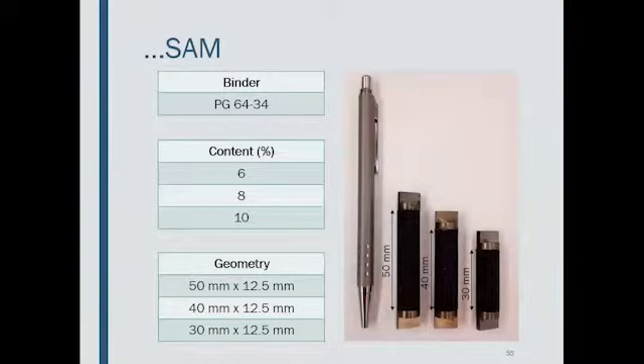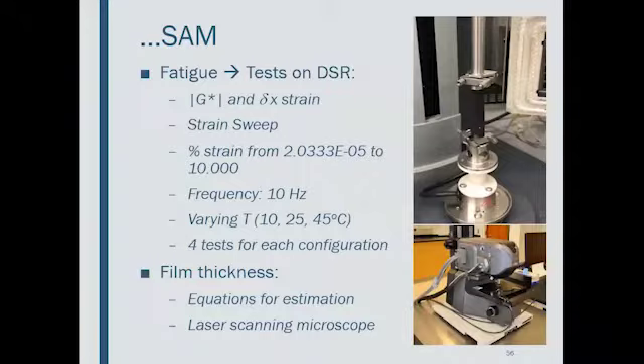In this period, we worked with one binder type, the PG 64-34. We varied the binder content at 6, 8, and 10%, and the geometry in terms of height at 50, 40, and 30 millimeters. We performed tests on the rheometer, and we are interested in finding the relation between the complex modulus, phase angle, and the strain. So we performed strain sweep tests where the frequency was fixed at 10 Hertz, and the percentage of strain varied in this range. We also varied the temperature for the tests at 10, 25, and 45 degrees Celsius. For each configuration, we worked with at least 4 tests, trying to check the repeatability of this methodology.